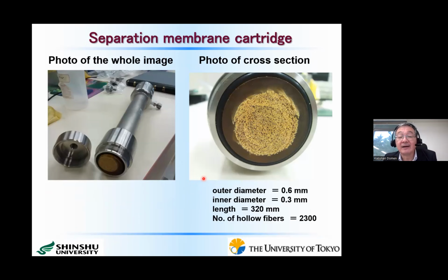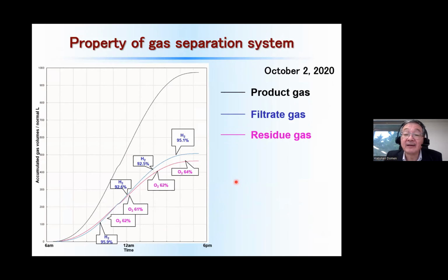And this is a real cartridge of such a system. As you see here, these are polyimide hollow fiber membranes. It contains about 2,300 hollow fibers, the length is 32 centimeters, and the inner diameter is 0.3 millimeter. Using this one, we carried out a separation experiment. In this particular case, almost all day was a clear day, and this is the accumulated amount of hydrogen and oxygen. This day we obtained about 1,000 liters of hydrogen and oxygen mixture.